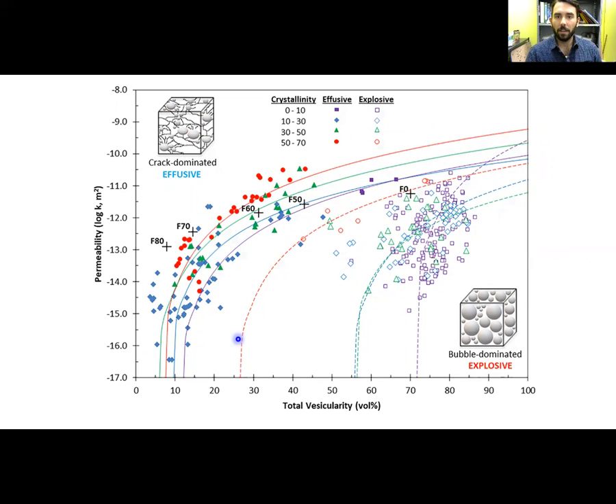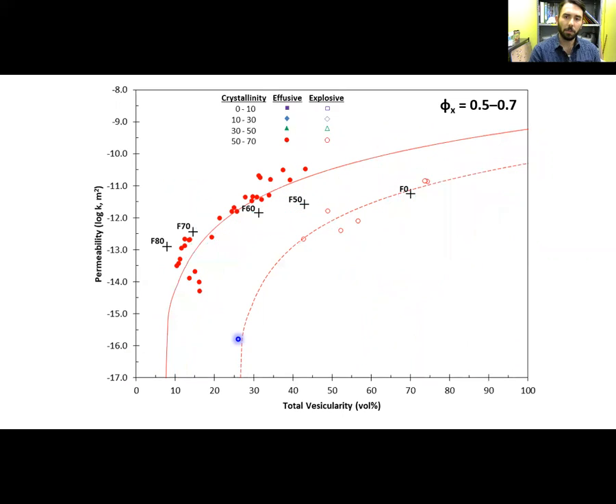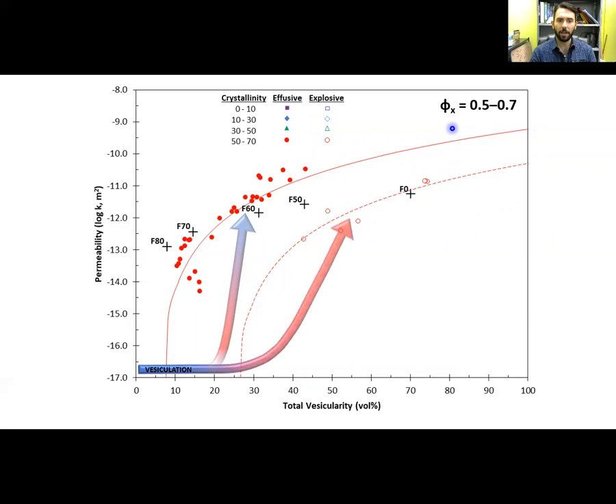Now, if we compare effusive versus explosive data for a single bin of crystal contents, we can easily observe that effusively erupted samples have lower porosities than their explosive counterparts. But we have yet to answer why explosive behavior occurs despite samples having high permeabilities. And we propose the key to explaining explosive potential lies not in the explosive data, but rather the percolation curves for effusive eruptions. Here we can clearly see there is a permeability threshold approximated by the curve for effusive lavas, at which outgassing proceeds rapidly enough that further permeability development terminates. In contrast, explosively erupted samples plot at lower permeability for a given porosity and were unable to reach the permeabilities necessary to outgas efficiently.